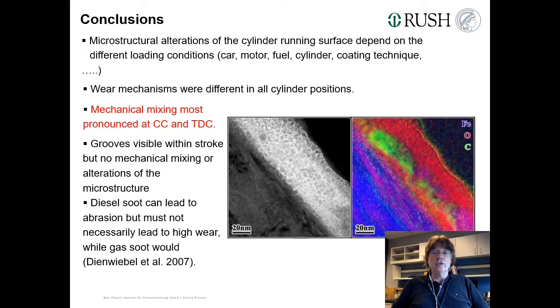So in this particular case, the mechanical mixing was most pronounced at the combustion chamber on top dead center, or more or less brought the story. It was about diesel engines, and we know, for instance, that diesel soot certainly can lead to abrasion, but must not necessarily lead to high wear. That has been shown by Martin Dienwiebel, because it has no dangling bonds on the outside, while gas soot is much more aggressive to the cylinder wall as well as to the piston ring.